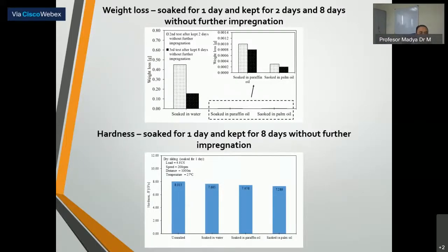Okay, this is the weight loss. Soak for 1 day and kept 2 days and 8 days without further impregnation. We can see that the weight loss when we soak in palm oil is not much different, which means that the lubricant is still in the pore or in the void of the material. And then we can see that the hardness is a bit reduced by soaking.